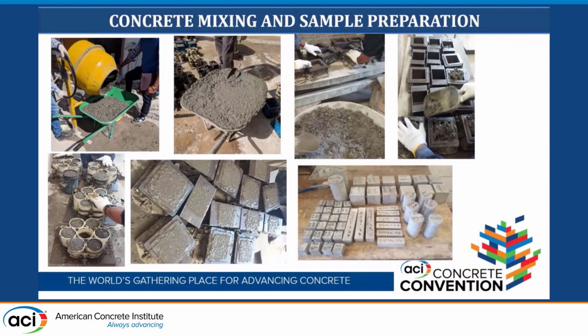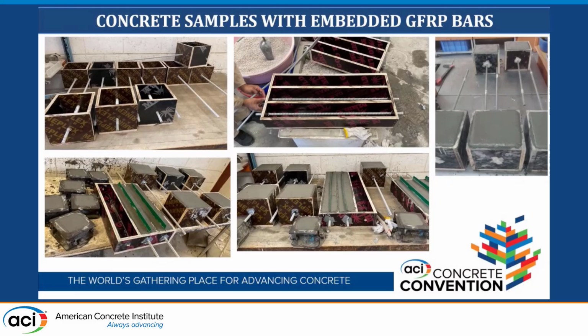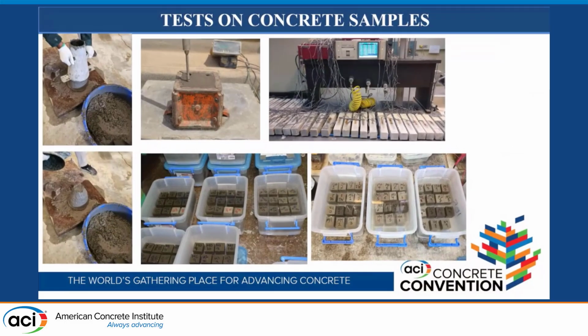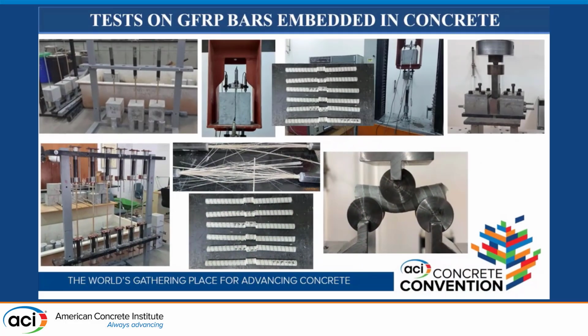So those are some of the pictures of the preparation of the samples. Then that's the GFRP bars embedded in concrete and kept for 3 to 6 months, and then we took them out and tested them, and measurement of shrinkage, and also long-term exposure of these concretes to acidic solution and to sulfate solution for at least 6 months. And those were the preparation of the samples for GFRP bars, which were tested in interlaminar shear and other shear.